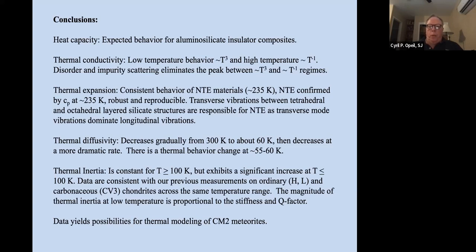There's a huge amount of scattering. These are disordered materials, and they also have high porosity. The thermal expansion shows consistent behavior, negative thermal expansion, particularly centered around 235 Kelvin, and it's confirmed, importantly, by heat capacity measurements. And the transverse vibrations between the tetrahedral and octahedral layer are responsible for this, as the transverse mode vibrations dominate longitudinal vibrations.